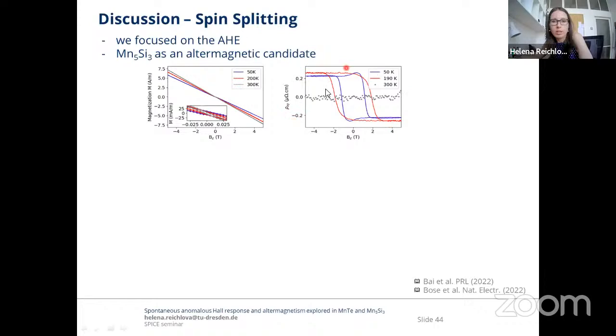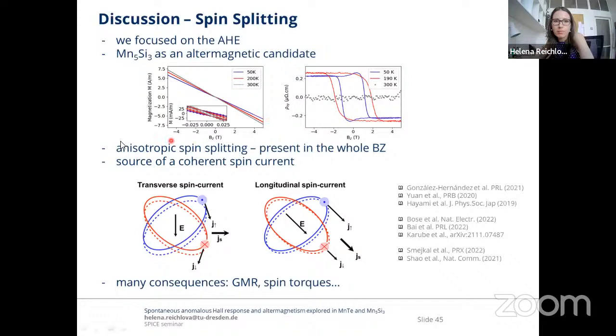However, it was also shown that the altermagnetism, because of this anisotropic spin splitting, can serve as an excellent source of a coherent spin current. This was already tested in the ruthenium dioxide pioneer. These three important papers show very nicely the spin torque experiments in ruthenium dioxide. And how does this actually work? Let me show it on this simplified cartoon.